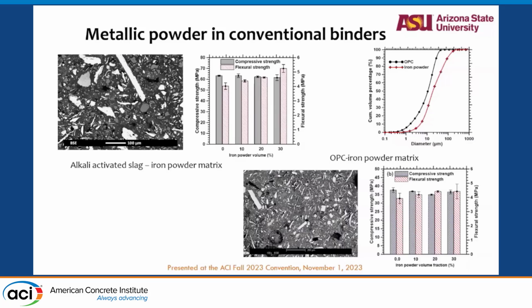So we added 10, 20 and 30% by volume of iron powder into the mix and checked for their compressive strength and flexural strength on the 28th day. You can see the iron particles are nearly in the range of the particle size of OPC, and there is little to no change in the compressive strength. You could say there is a slight decrease, but it's not significant. Flexural-wise, there is a slight increase in the strength of the mix.